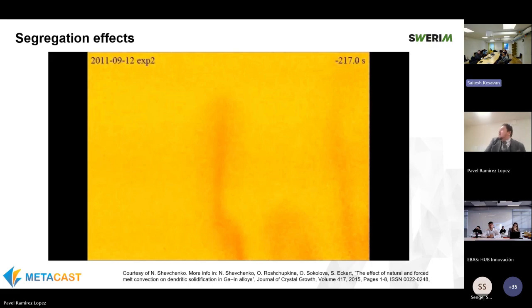As we keep progressing, even at some point, some of these islands, I think we have it in the previous video even better shown, can cause local remelting because of the change. This is at the end. You will see it here. I will stop it here for the online. So eventually we will have the formation of actual channels where we have this enriched solute that is escaping